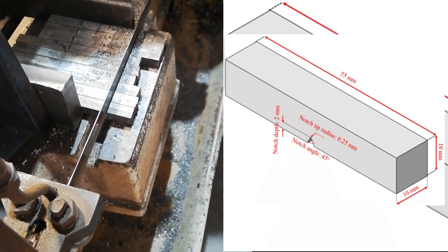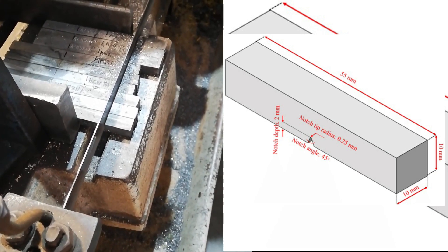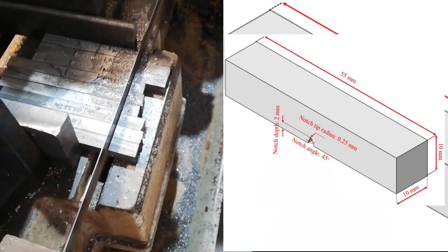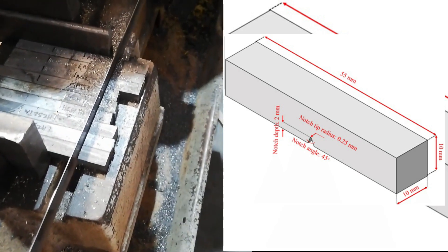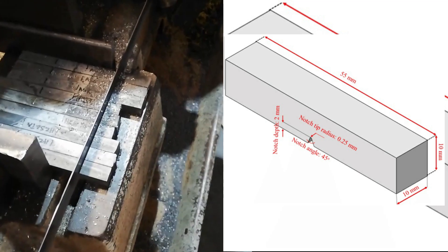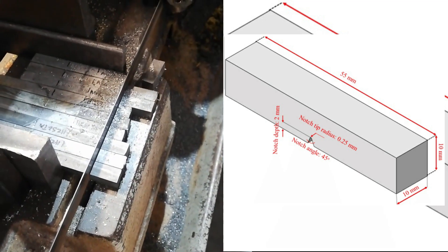In front of you we are cutting the sample to the standardized length which is 55 millimeter. After this the sample will be notched. The notch will be on the center of our 55 millimeter.